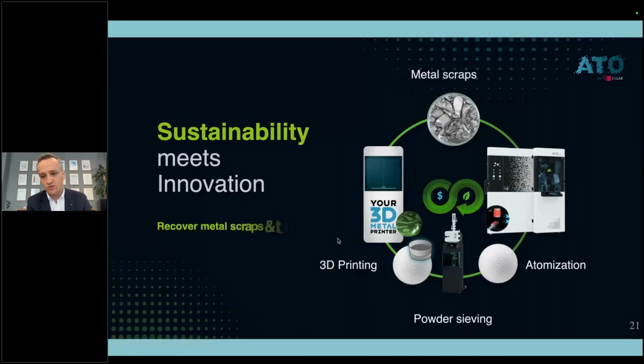With this solution, with the AtoLab Plus and induction melting system, we can achieve a full loop. I mean, we can recycle the material. We can recycle the scraps or CNC chips. We can atomize, turn into a perfectly spherical metal powder, then sieve, because it seems to be obvious that we need to sieve the material after the atomization process. Then, for example, we can go with this powder to a 3D metal printer with different technology, depending on the PSD you would like to work with, or for example, for cold spraying technology, and the leftover we can turn into a powder again.